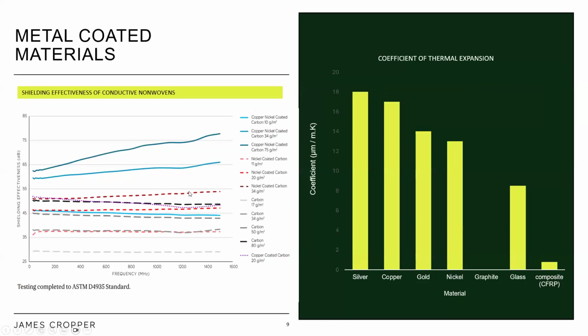Here we have 2 graphs that summarize some of the key benefits of our non-woven veils. On the left, the enhancement a metal coating delivers to the EMI performance of a carbon non-woven is really, really clear. We have shielding data from about 100 megahertz up to about 40 gigahertz. And on this graph, we're just going up to about 1.6 gigahertz. But as an example, if we take a 34-gram carbon veil, the shielding effectiveness is around about 45 dB, which is really, really good. However, if we apply a thin film of metal to the fiber, this enhances the shielding performance to around about 60 or 65 decibels, showing the improvements that can be gained by just coating our materials with a little bit of metal.